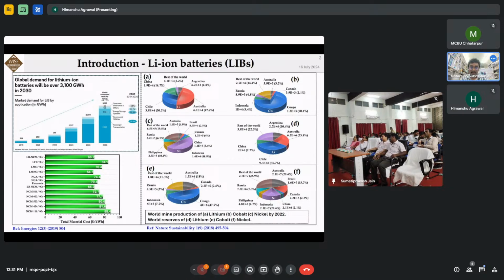That automatically indicates an upsurge in the price of raw materials. The raw materials for battery production on the cathode side are mostly lithium, nickel, cobalt, and manganese, and on the anode part, graphite, plus the separator part. Metals like lithium, cobalt, and nickel are mostly mined in particular countries. For lithium, you can see from that figure that Australia dominates. As of 2022, around 50% is mined from Australia alone. For cobalt, the Congo gives around 70% to the world.